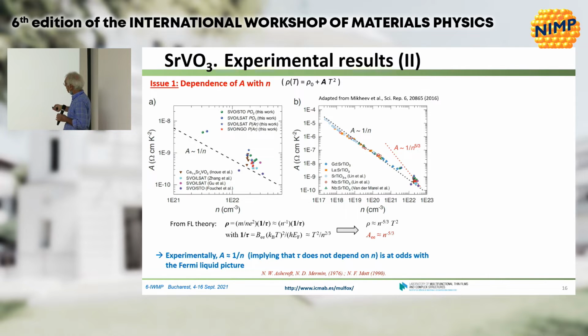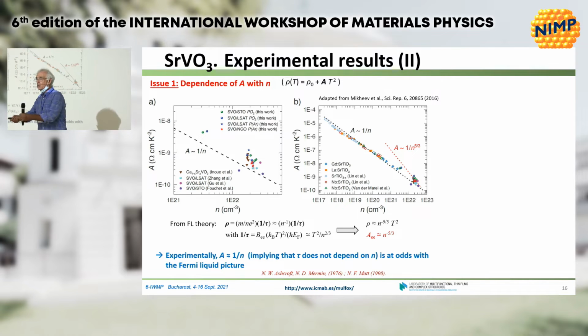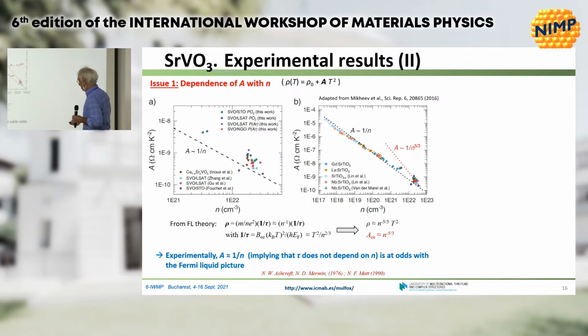This is 1 over n. This is the resistivity of a metal. It should be inversely proportional to n. So that's true: the amplitude of the resistance is inversely proportional to n. That's good, but it should also depend on the scattering. And this data shows the scattering term does not depend on n, which is at odds with what you would expect for a correlated metal. The more electrons you put in, the higher the scattering should be. This is not the case. The data doesn't show that. So here is a problem. Without going into the details, it's obvious that there is a problem here.